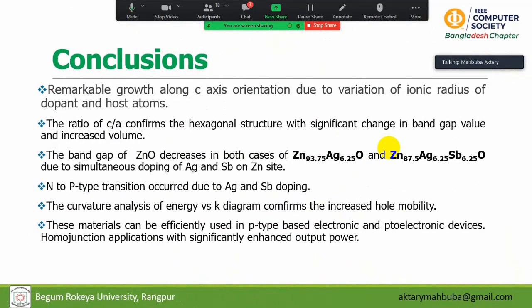The conclusion of my presentation or research finding is that the elongation of C-axis orientation due to variation of ionic radius size of dopant and host atoms, and the C over A ratio confirms the hexagonal structure, that is the unchanged phase of this material, and the band gap has tuned significantly for our future applications, and N-type to P-type transition occurs due to silver and antimony doping.